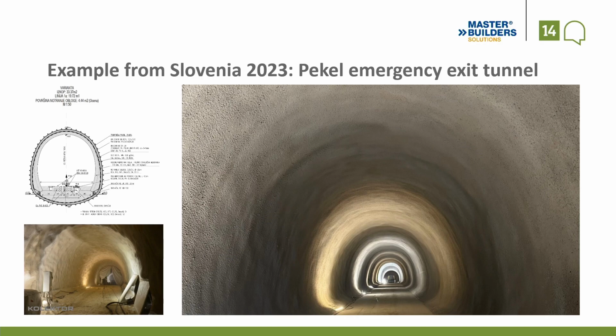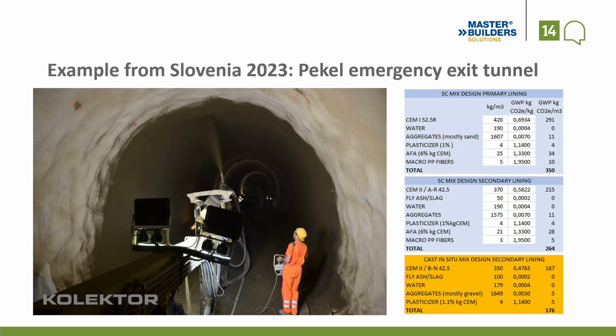I've heard that Andre is somewhere here, that even after heavy rainfall it was very dry inside. It did the job, obviously. And we have to do the mathematics on it, to be fair, because I started with that. That's the mixed designs, two spray applied linings. The lower one, for the permanent one, comes in with less heat, less cement, less reactive clinker to minimize the thermal shrinkage. Cast inner lining was not used.